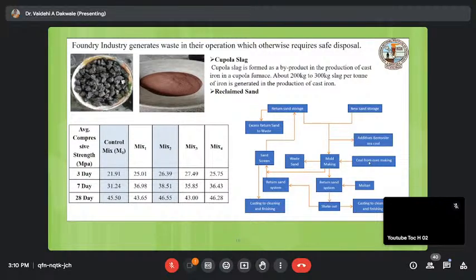So we used the cupola slag. We crushed it because there were bigger chunks of say 150 mm, 100 mm, and higher in uneven combinations, so we crushed them to the size and gradation of our natural aggregate. Then we used the reclaimed sand, which is reclaimed from the mold-making process for casting through washing and cleaning. The same sand is used for 2-3 cycles of sand molds, after which it becomes waste. We used these two, made some mixes of M40 grade concrete, and found that yes, we can use this aggregate.